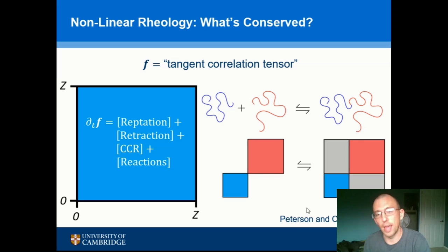And then once you've done that, if you're interested in the fast breaking limit, you can do the same kind of asymptotic analysis and boundary layer analysis that we put together for the reptation case, and you come up with a dramatically simplified constitutive model that can be effectively solved with excellent accuracy in as few as 6 modes. And so it's totally suitable for CFD applications.